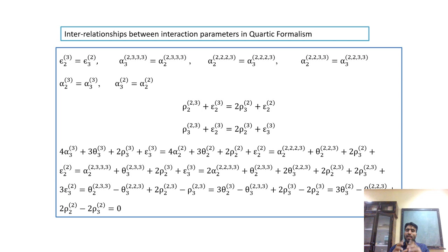In the fourth order truncation of the Taylor series, we obtain interrelationships as well. The same type of interrelationships are obtained if we consider thermodynamic consistency in the Wagner's Taylor series. That series is not thermodynamically consistent except as an infinite Taylor series, but we can make it thermodynamically consistent by obeying the Gibbs-Duhem equation, which yields these interrelationships.